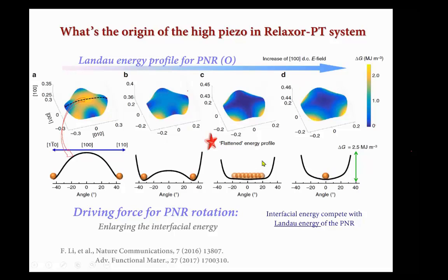Based on this, it is worth comparing this study with the earlier report on phonon studies by Dr. Guangyong Xu. Phonon studies show that the PNR and phonon interaction can induce a phase instability. They soften the transverse acoustic mode and increase the elastic compliance. In our model here, it is proposed that PNR facilitates the polarization rotation and enhances the transverse dielectric response, through the competition of the interfacial energy and the Landau energy. These are local energy competitions.